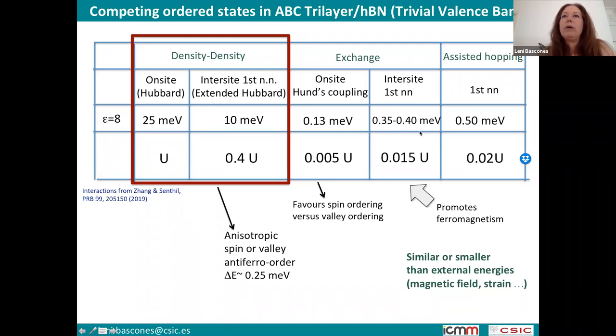But what is more interesting is the fact that we have this intersite first nearest neighbor. And if we compare that with the energy of the antiferromagnetic state that we find, they are of the same order of magnitude. So at this point, one cannot say which one is larger, because it's the same order of magnitude, but it could be that it is the one that disappears. So what is more important, I think, is the fact that they have similar or even smaller energies than the external energies that we can use. So it can be possible that there are possibilities to tune, or that they're going to be competing.